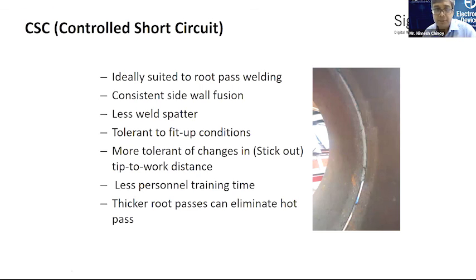This will help you increase your productivity up to about 30%. Ideally suited for root welds, consistent sidewall fusion, less spatter, tolerant to fit-up conditions, and more tolerant to changes in stick-out. Less personnel training time and thicker root passes can eliminate the hot pass.